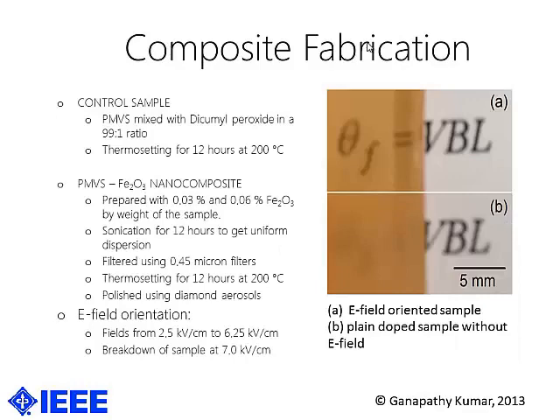For the composite fabrication, we used a control sample, and in addition to that, we also used the nanocomposite, where we doped it with concentrations of 0.03% and 0.06% of the iron oxide. We didn't want to compromise on the optical clarity, hence those particular numbers. They are arbitrary. So the composite was sonicated for 12 hours to get a uniform dispersion, and we filtered it using 0.45 micron filters, and the final composite was polished using diamond aerosols.